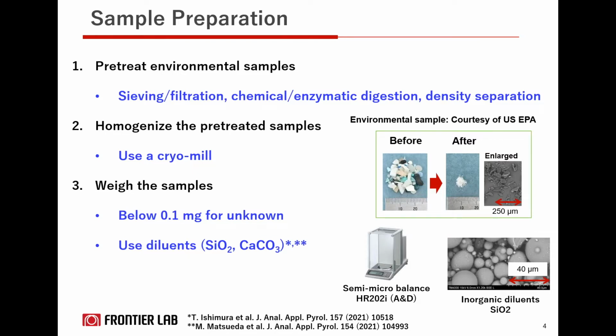So in terms of sample preparation, microplastics are typically extracted from environmental samples by performing appropriate pretreatment and then homogenized using a grinder or a mixer. Then you can place your unknown sample or the standard sample into your sample cup and weigh it using your microbalance in most cases. However, as part of our calibration kit, you get the diluents of SiO2 and CaCO3, which you can see here, that they allow you to eliminate the need to have a microbalance. So you can use a semi-microbalance and prepare your own calibration standards to measure small amount of samples as well.